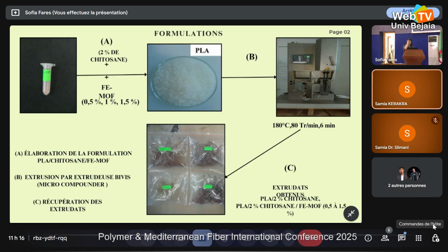Next, please. So here the formulations were prepared using a twin screw micro extruder designed for small scale melt processing. For all materials used here, PLA as matrix and Chitosan as antimicrobial agent were dried at 60 degrees Celsius for 24 hours before processing. For each formulation, about 12 grams of PLA, pure or blended with fillers, were loaded into the preheated chamber at 180 degrees Celsius. Two series of experiments were performed.